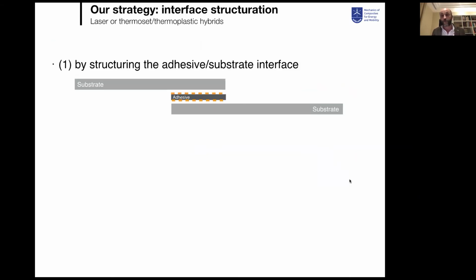In the team, we work on three strategies that are all about bringing progressivity to the failure, because you know that the main problem in adhesive bonding today is not the intrinsic performance. That means we can get quite good adhesive joints today. The problem is that these joints are very brittle, and when they start to fail, they experience an unstable failure. So the whole strategy here is to make sure that we bring progressivity in the failure of the joint. We do this in different ways.